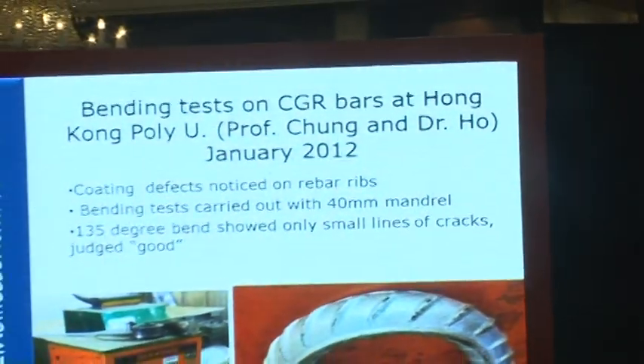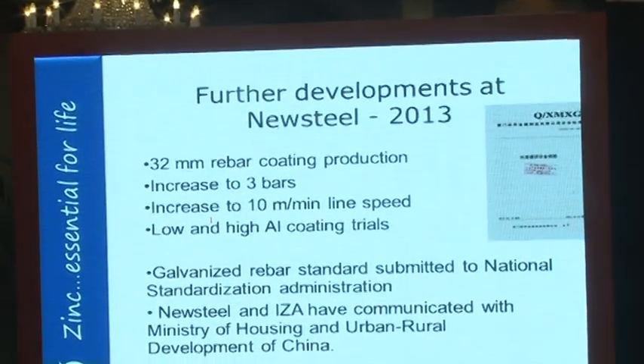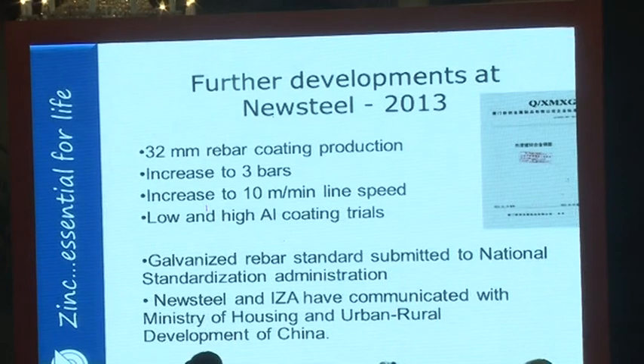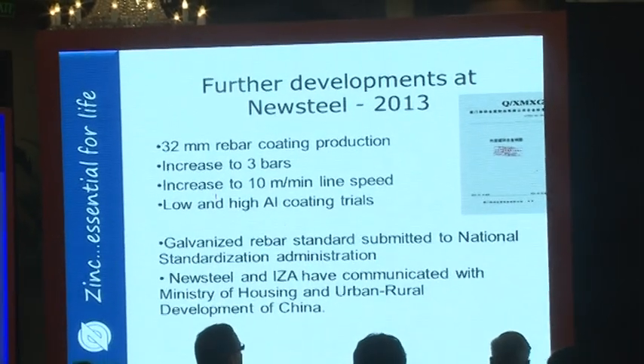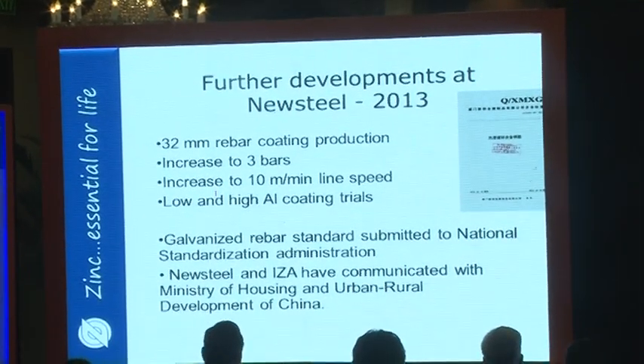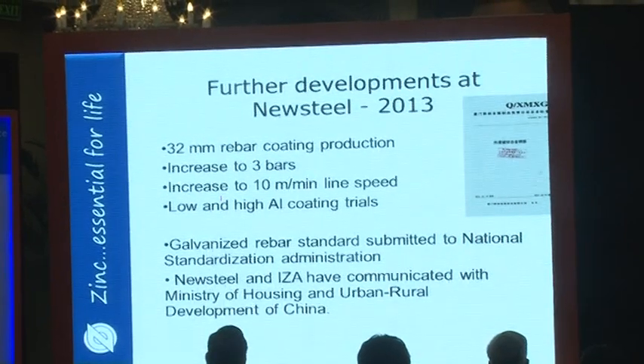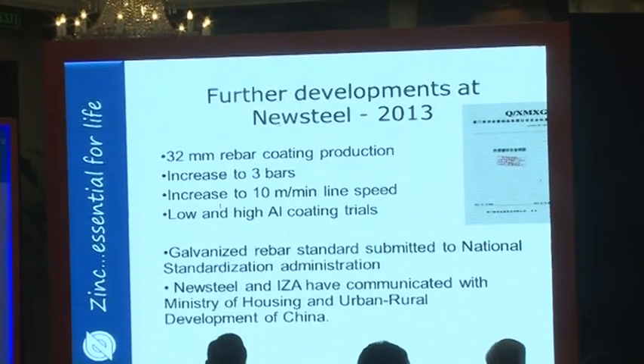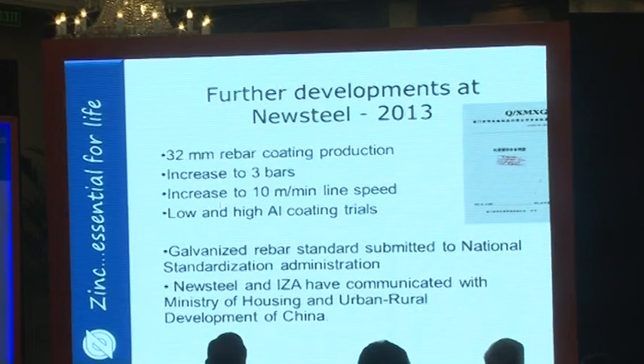So we then went on to do bending tests at Hong Kong Polytechnic University, and this showed that we were able to do these mandrels up to 40 millimeters, and we never had any problems there. And so that's several times the rebar diameter. And then we went up to a 3-strand line. The producer was encouraged enough to work at 3 bars and 10 meters a minute. So that is where we are now. We're running 10 meters a minute with a 3-bar line.